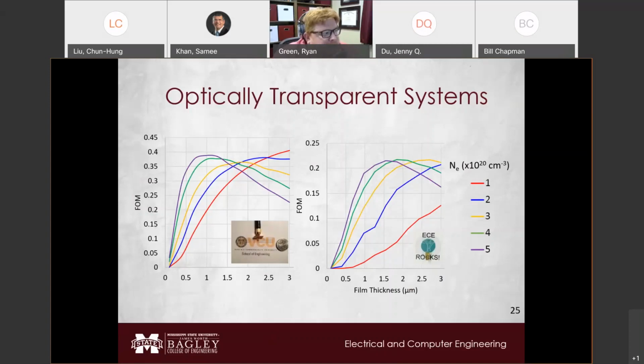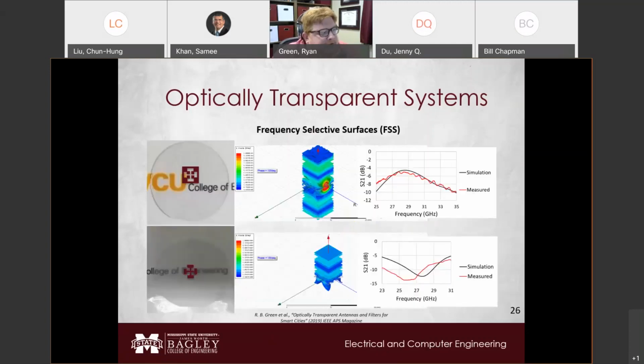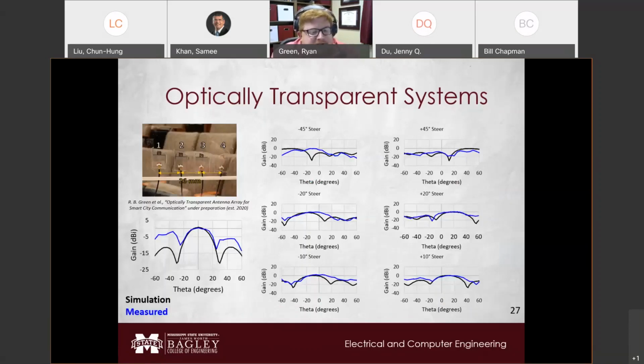We also studied if these kinds of systems could be applied to things called frequency selective surfaces, or filters. And what we found is that it's actually quite different. There is some difference in our simulation of a frequency selective filter based off of material property, but it's nowhere near as drastic as something like an antenna would be, or at least a traditional antenna that involves surface currents, like a patch or a dipole. And we found that you can design a frequency selective surface that's bandpass, and it still acts as a bandpass filter, and you could design a band stop and it still acts like a band stop filter.